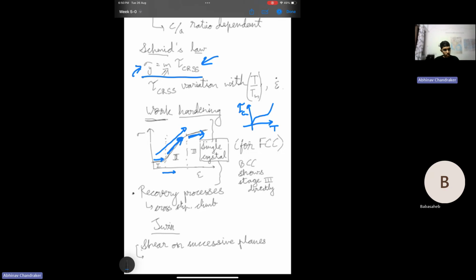So because of all of these recovery related phenomena, it will become easier, not exactly easier, but the rate of hardening will decrease because other mechanisms have also kicked in. Even though stresses are still high, the rate of increase is lower. So that is where recovery has started to also dominate stage 3.